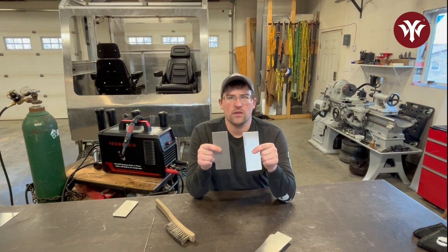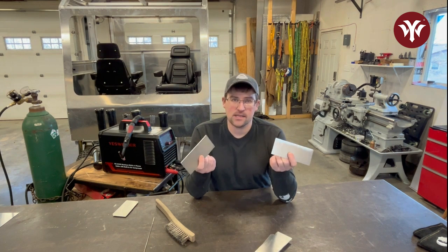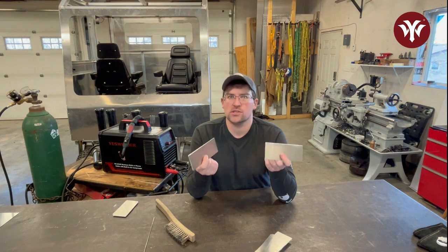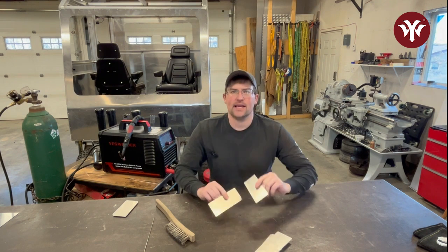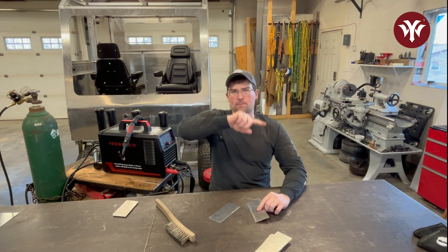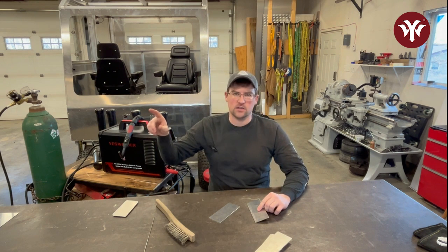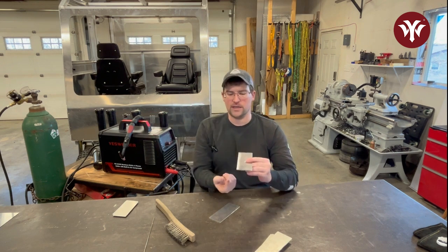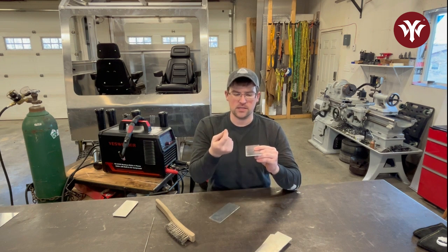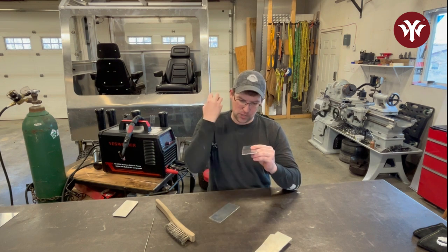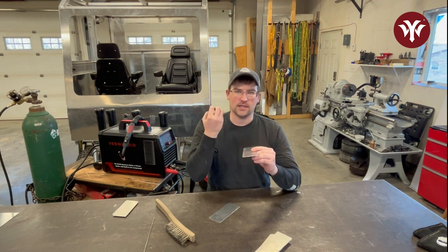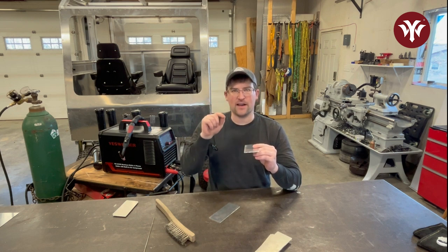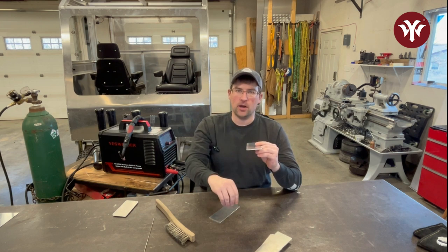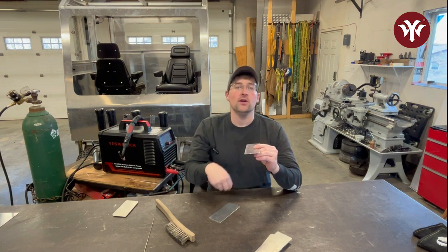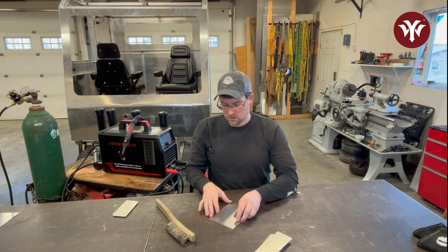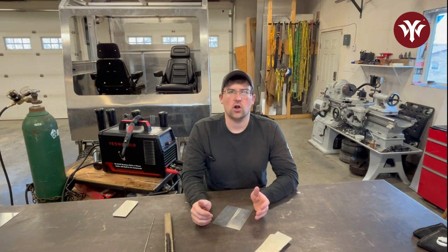So the other thing I want to talk about with aluminum, we're using AC to weld with and not DC like most other types of welding. And the reason we're using AC is a sine wave. It's got a positive half cycle and a negative half cycle. In the positive half cycle, the electrons are coming out of the part to the tungsten, and what that's doing is burning off or cleaning that oxide layer. And the negative half cycle is moving electrons back into the part, which puts heat into the base metal, creating your weld puddle.